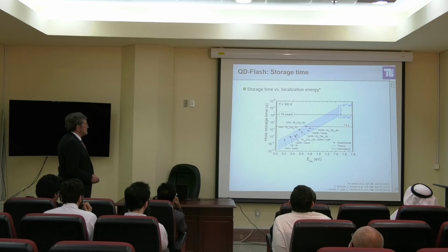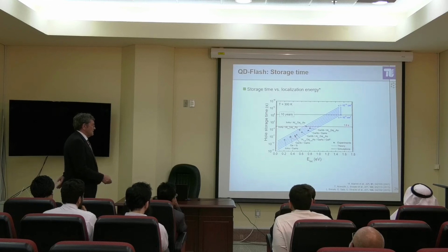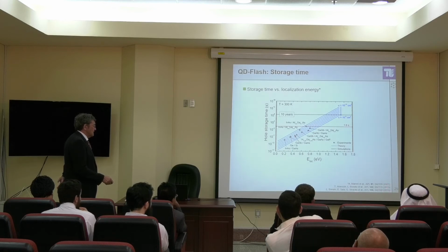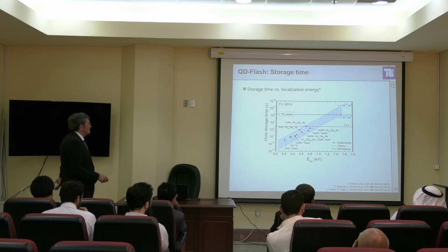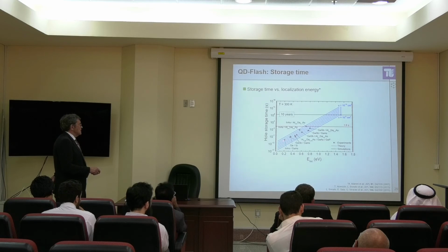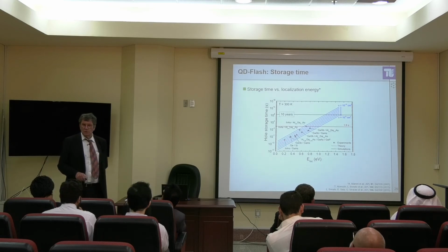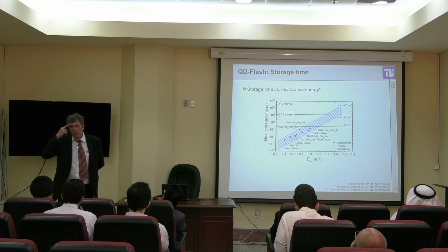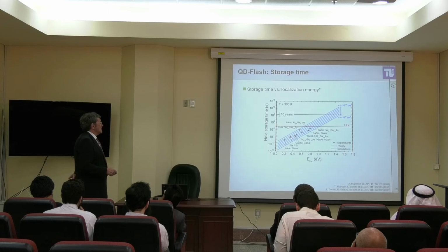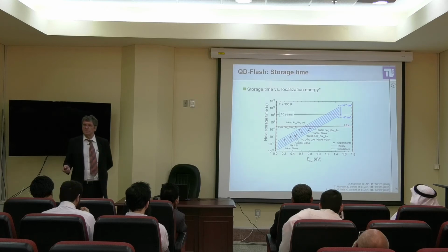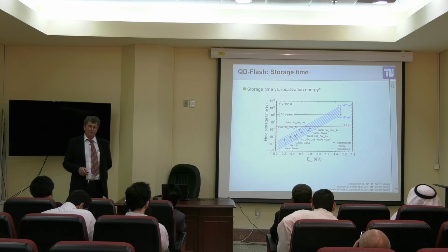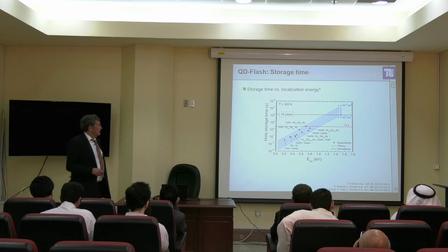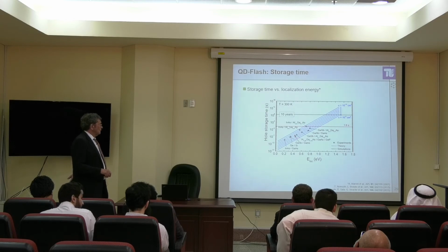Now here I have collected data. We have worked on this subject for quite some time, and we had several generations of PhD students. You see 2007, 2013, 2015. Here Sala appears for the first time. We started with this material system, which had a type 1 band structure, and which turned out, after some thinking, to be inappropriate. Then we went to type 2 systems, silicon germanium. We would have loved it if germanium quantum dots in silicon had worked out. Unfortunately, the binding potential is too little. Then we went to antimonides, and we are still with antimonides.